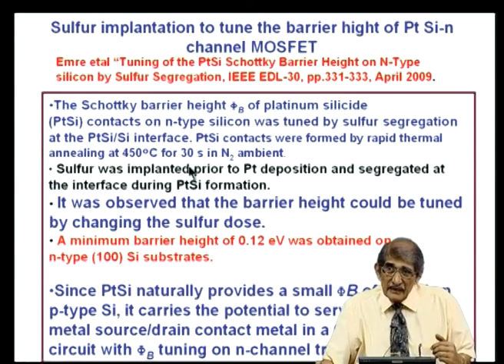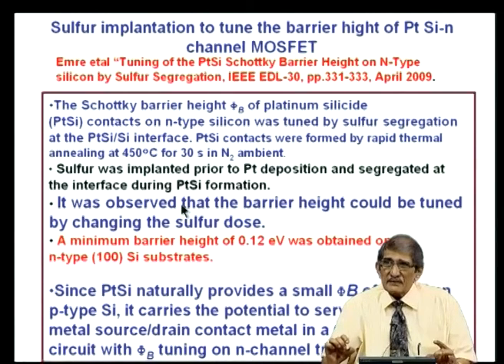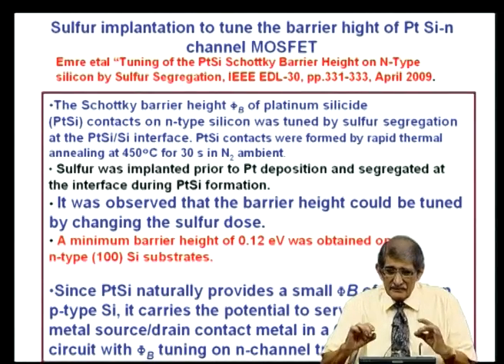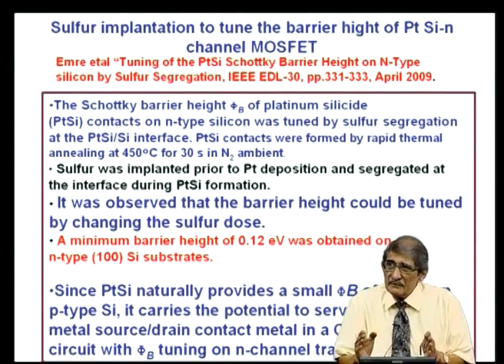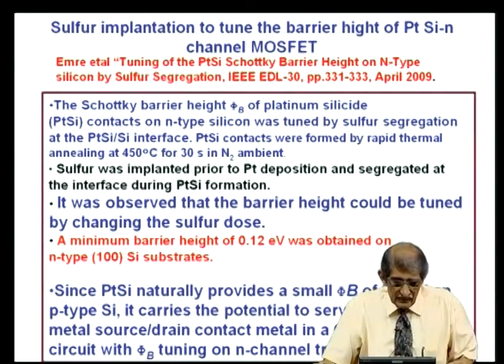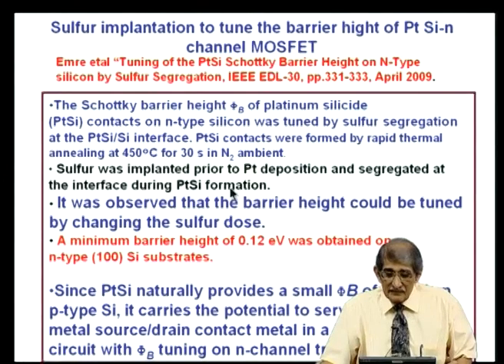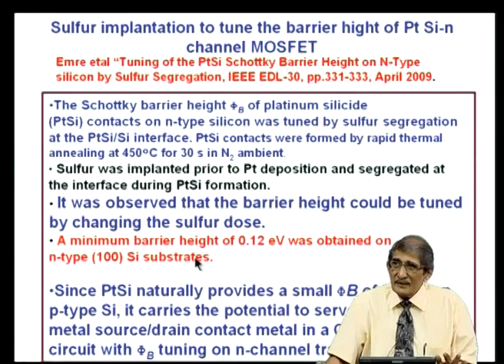If you keep it long enough at 450 degree centigrade, the sulfur may come out. Now, what happens? It just segregates into the interface. Platinum silicide is formed, it is just segregating. Segregating means it is getting a cluster of sulfur at the platinum silicide silicon surface. It was observed that barrier height could be tuned by changing the sulfur dose. A minimum barrier height of 0.12 electron volts was observed on n-type 100 silicon surface. That is very good news.